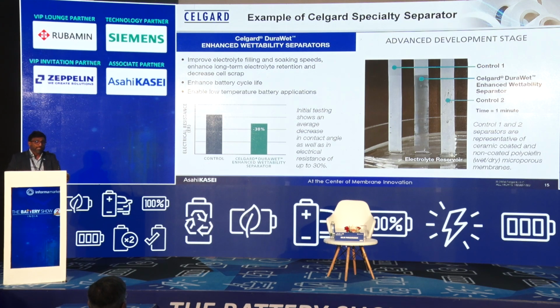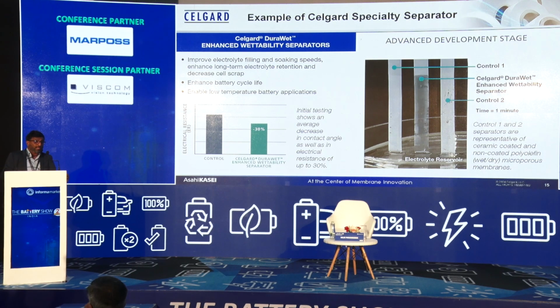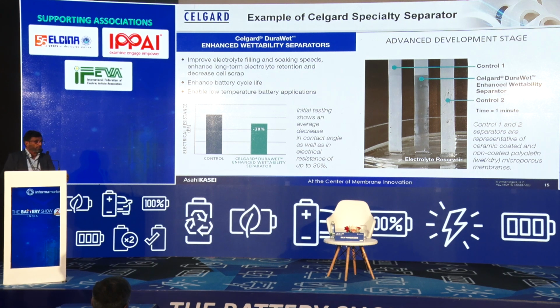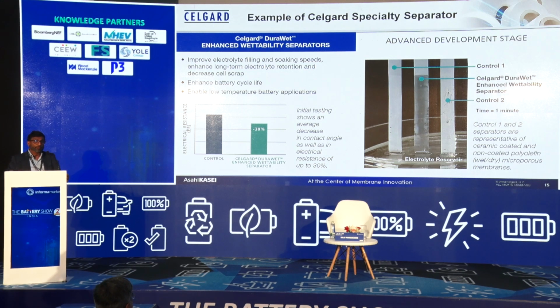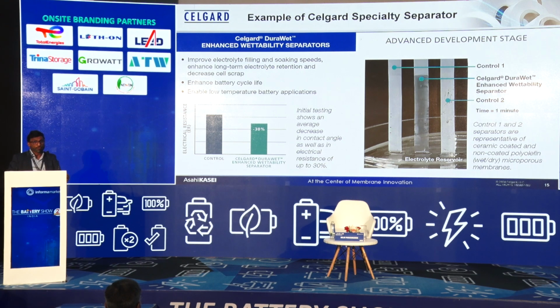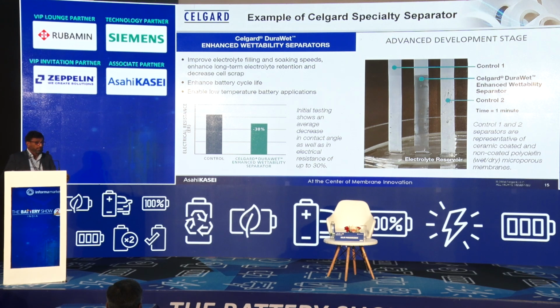So normally polypropylene is not very hydrophilic, it is hydrophobic. Now advancement has gone into the separators, so we are able to make the separator hydrophilic. With the recent coating technologies that we have adopted, our separators can increase the water wettability by 30%. So now it can increase the performance and can be used for other battery technologies like sodium ion, and most of the other high energy density lithium ion batteries, which call for higher wettability. This can drastically reduce the electrolyte filling time and increase the performance of the lithium ion batteries.